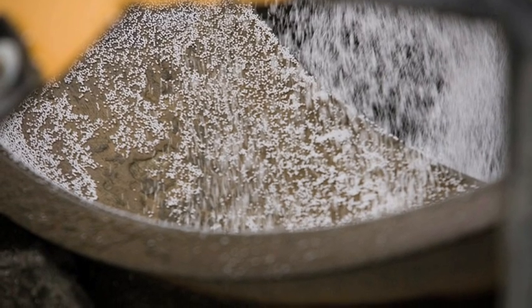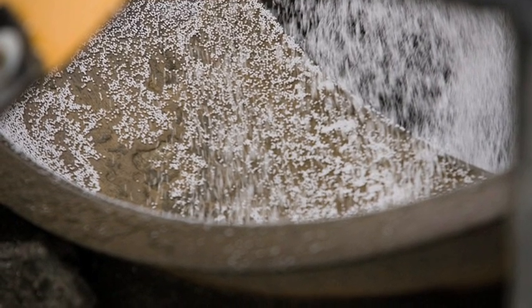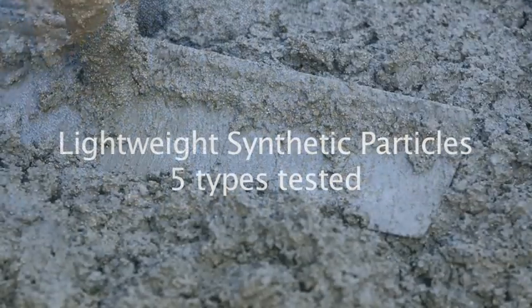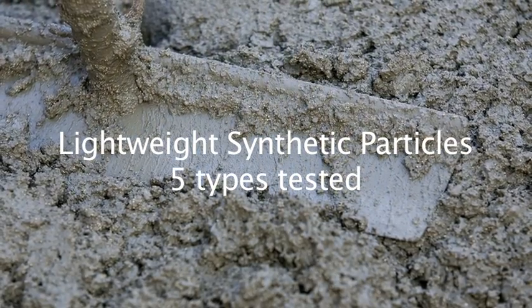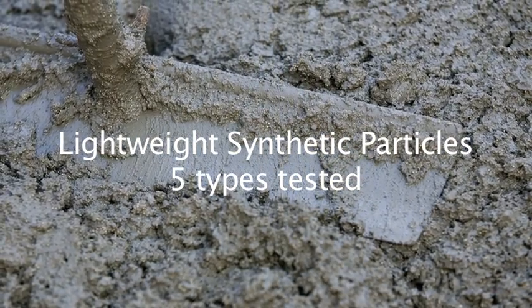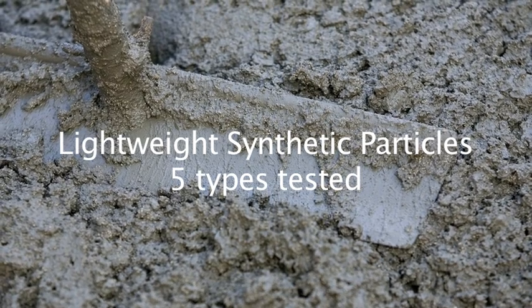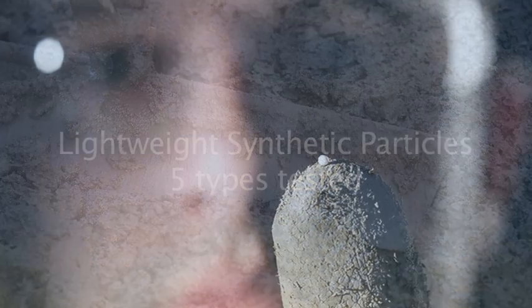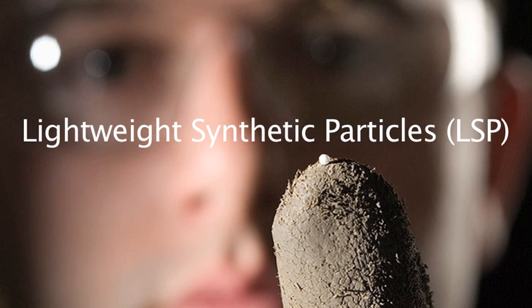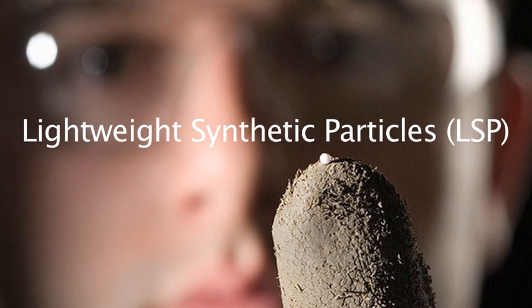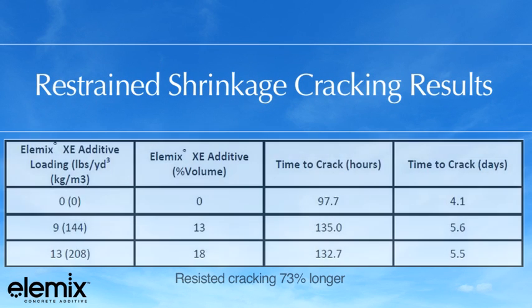5 types of lightweight synthetic particles, LSP, were used in testing. Fine aggregate passing the number 16 size sieve and retained by the number 30 size sieve were replaced by LSP. Various volume percentages of each type of LSP were tested, up to a maximum of 18% absolute volume. The commercially available LSP Elemix XE additive resisted cracking an average of 73% longer than the control sample.